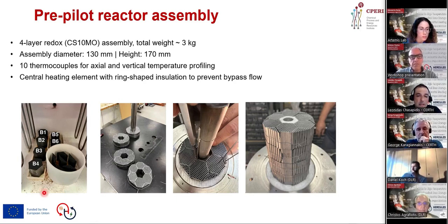So these segments were cut carefully and packed to form the honeycomb-like core of the reactor. The honeycomb geometry provides mechanical stability, but also ensures good gas permeability and efficient heat transfer between the solid material and the flowing gases. The pre-pilot reactor assembly consists of 4 layers of these hexagonal segment elements. The central channel houses the heating element, which provides the necessary energy input for the reduction phase.